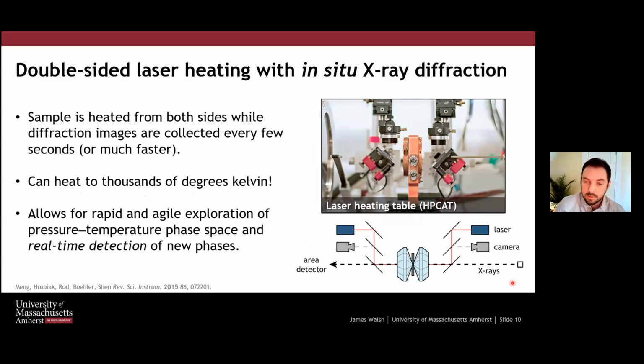So this is the laser heating table at HPCAT, sector 16, at the Advanced Photon Source. What we're doing is heating the sample from both sides. These are optical mirrors that are placed in the beam path. So the beam is going through everything, but we can move these mirrors in, and that allows us to direct laser light from both sides, upstream and downstream. So heating the sample from both sides to extraordinarily high temperatures. We can actually get to thousands of degrees Kelvin with this approach.